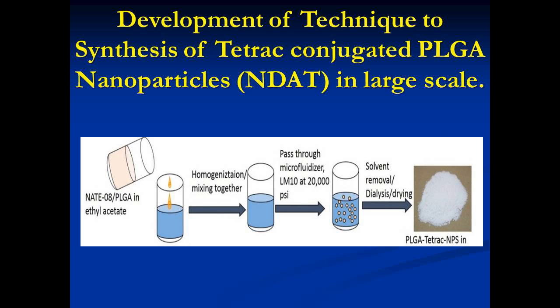Basically, you can mix some ethyl acetate, PLGA, and NATE-08, which is our tetrac-conjugated PLGA polymer. Then we do the homogenization with either a magnetic stirrer or a homogenizer. Then we can use this machine, the LM10, and at 20,000 psi we can make nanoparticles of around 120 to 150 nanometers. You can remove the solvent either by dialysis or TFF, and you can lyophilize it to get the PLGA-tetrac nanoparticles in powdered form.